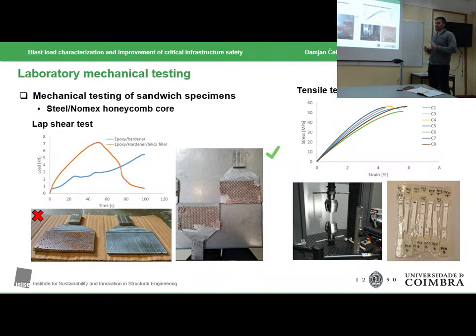In terms of mechanical properties, you are satisfied? Yeah, we are satisfied because they all achieved the prescribed strength. And there is no prescription about Young's modulus, for example? We have a range of Young's modulus values. I don't have here the information for the coefficient of variation, but there is always a range because there is always a certain slippage in the clamps. This also took a bit of time to figure out which clamps work the best. We tried, for example, to roughen the surface a bit with sanding paper. Then we tried one set of clamps, another set of clamps, we even tried to glue steel plates to increase the thickness in the contact. In the end, we found one set of clamps which performed the best. So maybe some variation also comes from the slippage. The stiffness will be lower if the element moves a bit. So Young's modulus is not specified in the data sheet.